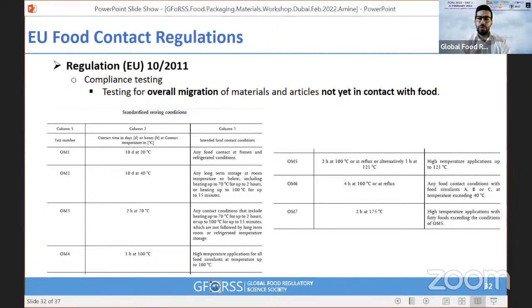In the case of overall migration tests, we also have very clear specifications based on the EU regulation. What's interesting to mention is that any long-term storage at room temperature or below should be simulated by a test or accelerated testing conditions for 10 days at 40 degrees.